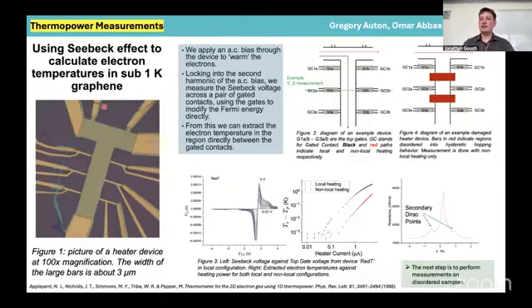So another project that's more related to what I'll talk about is thermopower or electron heating. This takes place in something like this T-shaped Hall bar, where essentially you apply a large current to the T end, which results in a large Joule heating, and then you track how that heat is dissipated along this relaxation channel here. And you track the temperature using Seebeck measurements with these pairs of gated arms.